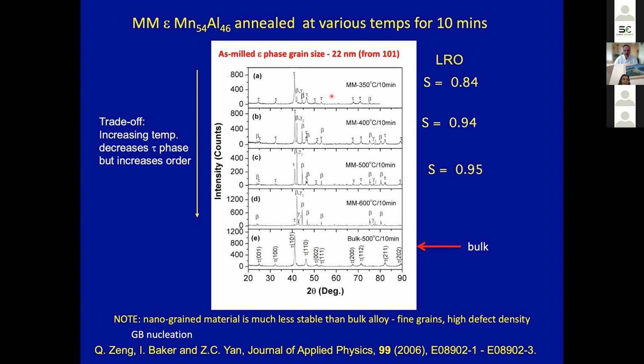By comparison, if you look at the mechanically milled material, at low temperature, you've got mostly tau phase, but there's also a little bit of beta and gamma 2 produced. As you increase the annealing temperature, you actually get less tau phase produced and more of the equilibrium phase. But interestingly, while doing that, if you look at the peak ratios, you find that the tau is actually slightly more ordered as you go to higher temperatures. So there's a bit of a trade-off between having less tau in the material and having it more ordered, so more magnetic.